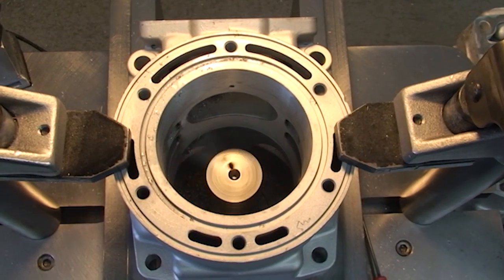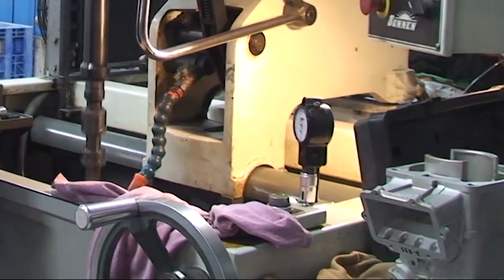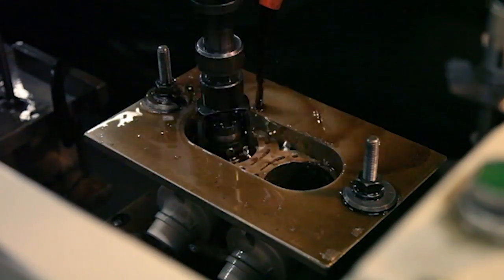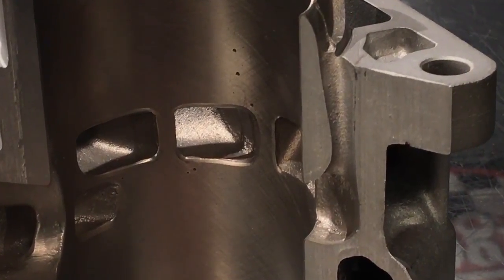These tiny bubbles of gas remain hidden in the casting until the casting is machined. When the cylinder is machined as new, or when a used cylinder is stripped, bored, or welded while being repaired, these gas bubbles are uncovered and look like tiny pits in the cylinder.